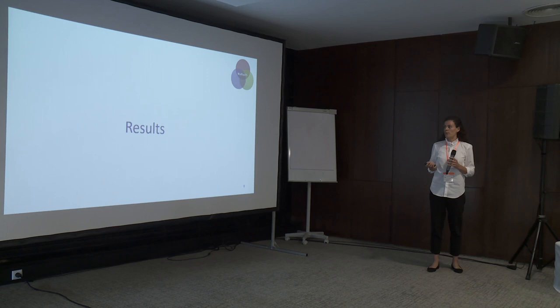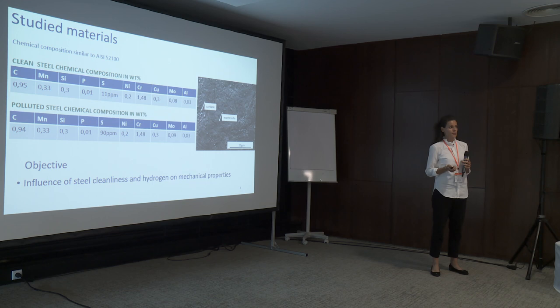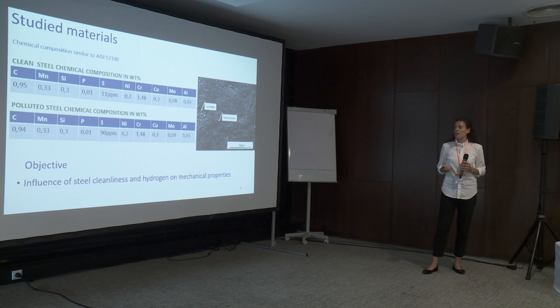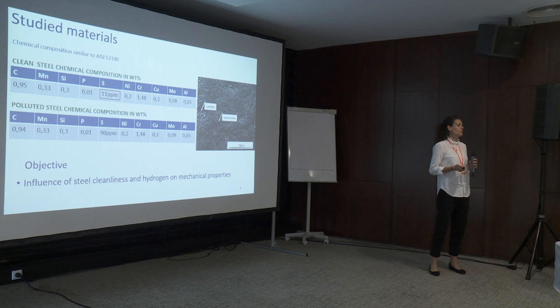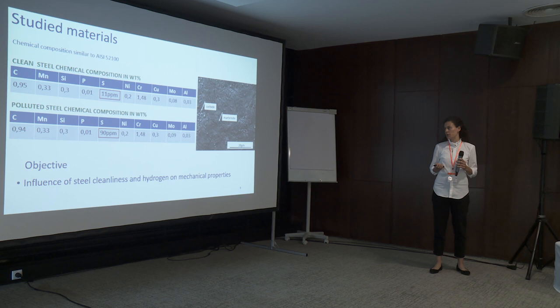In this study, two materials were laboratory cast, both very similar to bearing steel 52100 with high carbon and chromium content. In the first material, sulfur content was kept as low as possible to result in a lower amount of non-metallic inclusions. In the second, sulfur was kept close to the standard. Heat treatment was low-temperature tempering according to the bearing steel standard, resulting in a martensitic microstructure with some proeutectoid carbides.